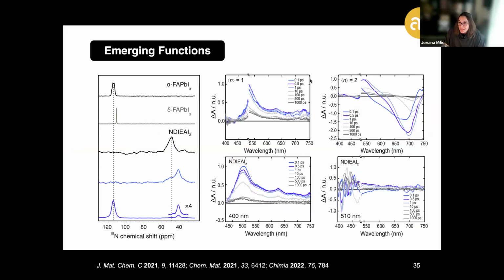With incorporating such systems in extended Dion-Jacobson-like architectures, one can stabilize the resulting structures even in these notoriously unstable formamidinium lead iodide systems, as illustrated by solid state NMR spectroscopy, in this case nitrogen-15 NMR, indicating in presence of these spacers and layer systems the stabilization of the desired perovskite alpha formamidinium lead iodide phase.